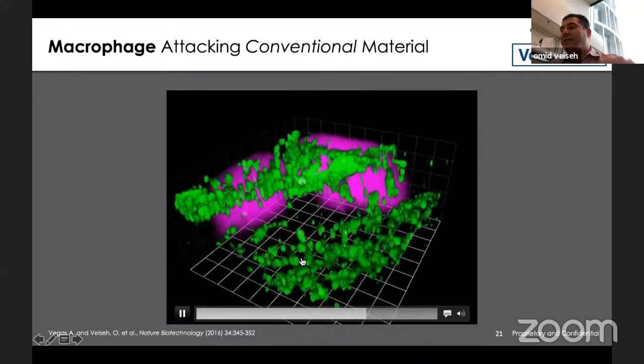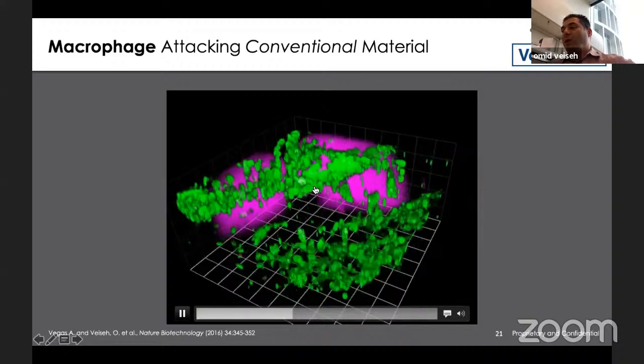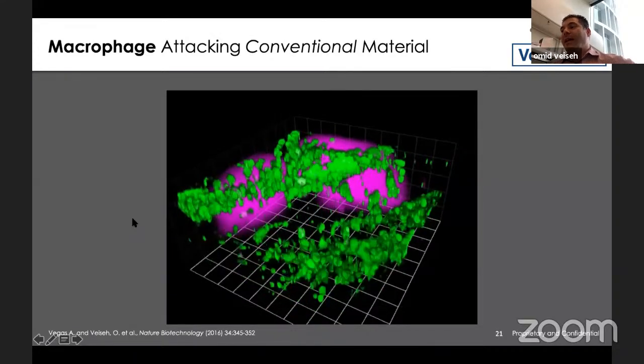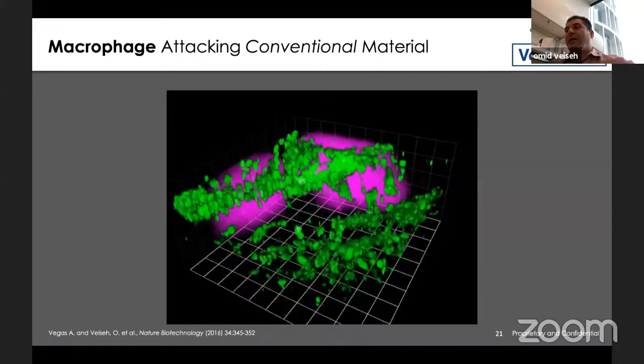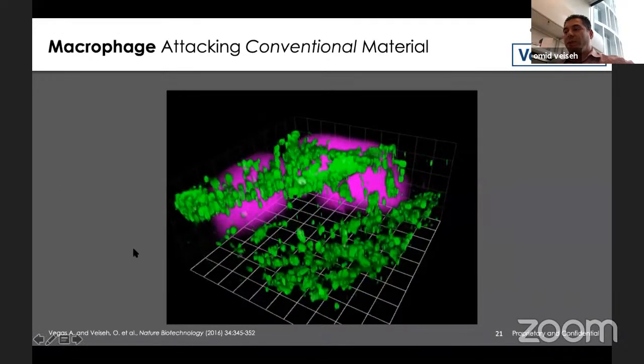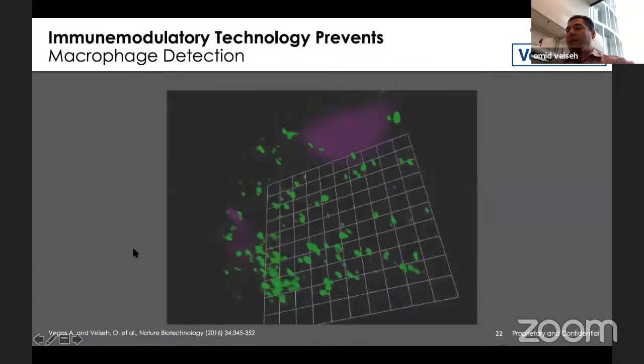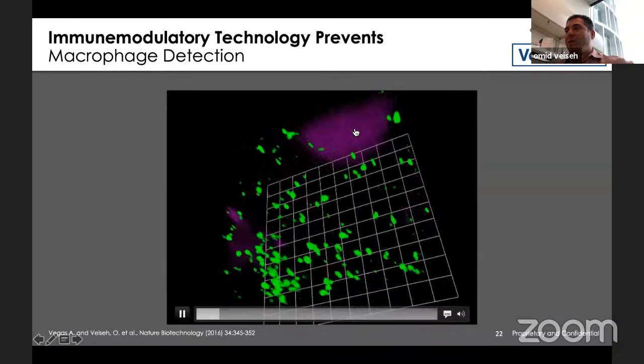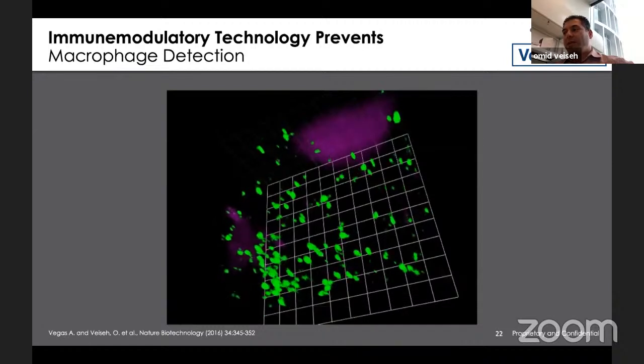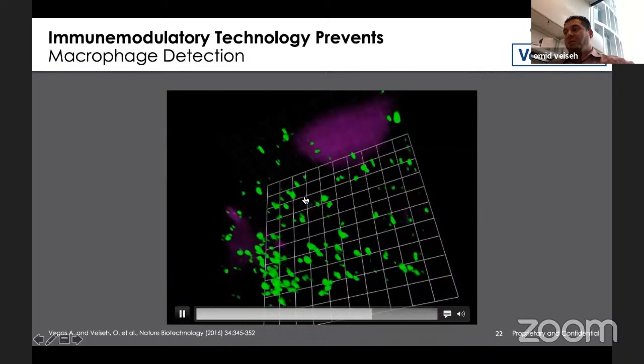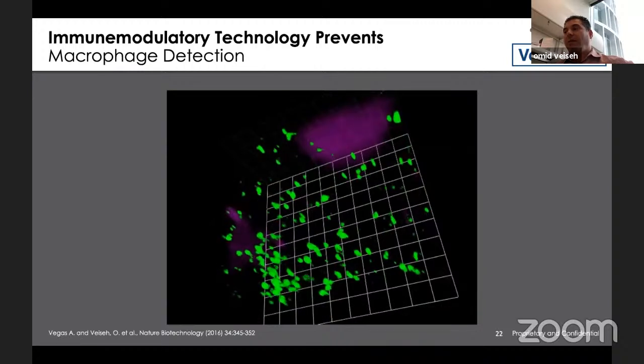You can see the immune cells are quite active. There's a lot of them there. More and more are coming in. And really, this is an activated immune response mounted against the biomaterial. This is the scar tissue formation that we're trying to address. What's fascinating is that when we have the same exact situation, but the material has our small molecule coating, you can see that there are immune cells there. They're present in healthy numbers, but the immune cells are crawling on the surface of the material, and they're not adhering. When they don't adhere, they don't become activated. They're just harmonizing with the immune system, and there is no foreign body response that gets initiated.